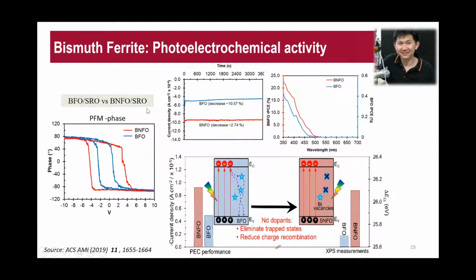So here we have two different materials. One is BFO, another is Nd-doped BFO. This is a thin film, and we want to study this material in response to photoelectrochemical activity. And we understand that BFO is a highly leaky material. It's already been reported. And so we use our PFM to analyze the phase. And we sort of found that